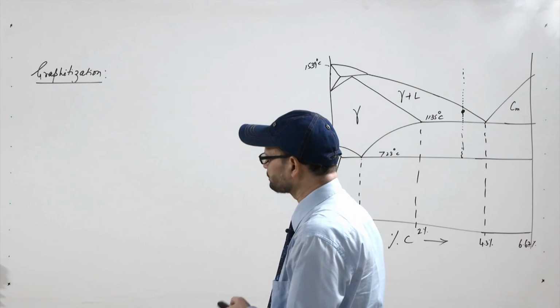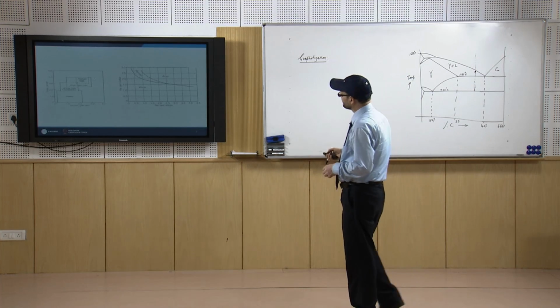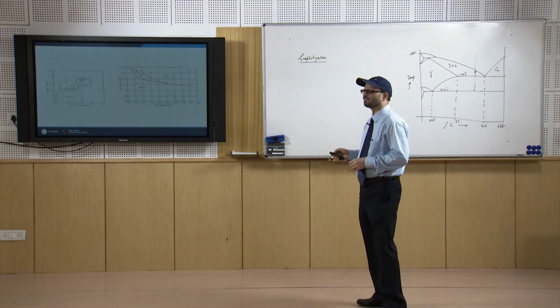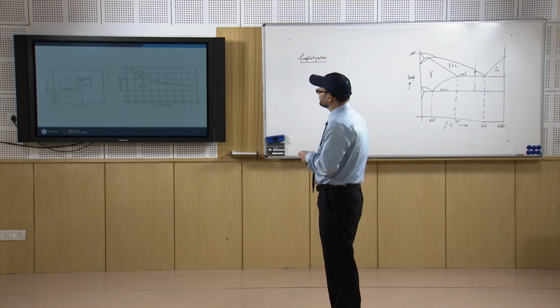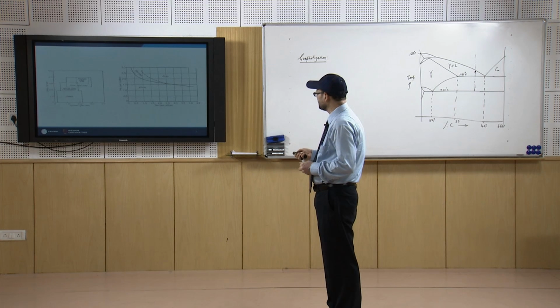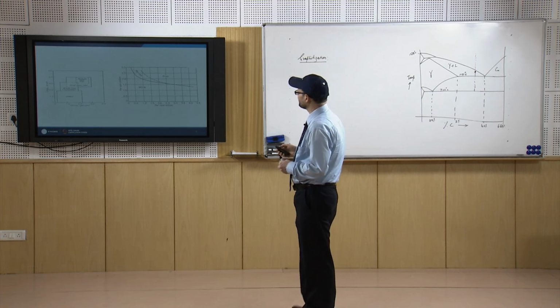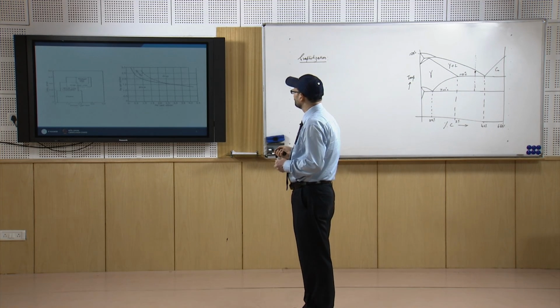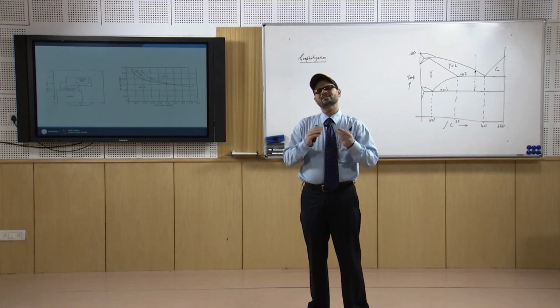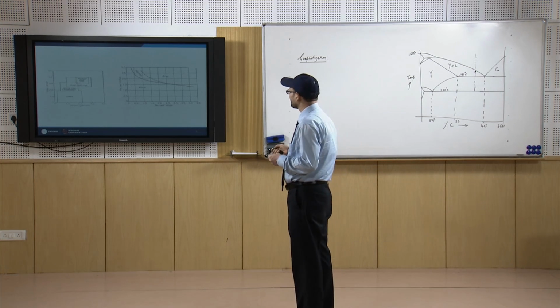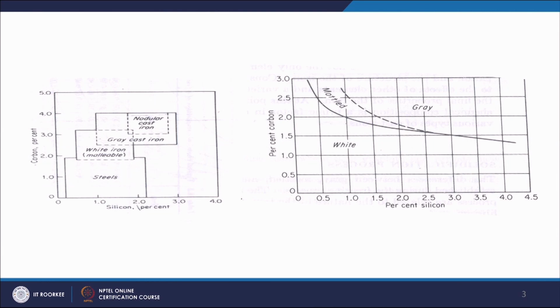So, we can look at this figure, which tells that there are varieties of cast iron, as I told. As we see in the case of steels, the silicon percentage is maximum 2, but in cast iron it goes up to 3 or 4 even. When the silicon percentage is more, we see that this is grey cast iron. When silicon is more, there will be more graphitization and carbon will be separated as graphite structure. That is why you get grey cast iron, whereas when the silicon is less, you get the white cast iron. If the carbon percentage is up to 2%, you have the variety of steels.